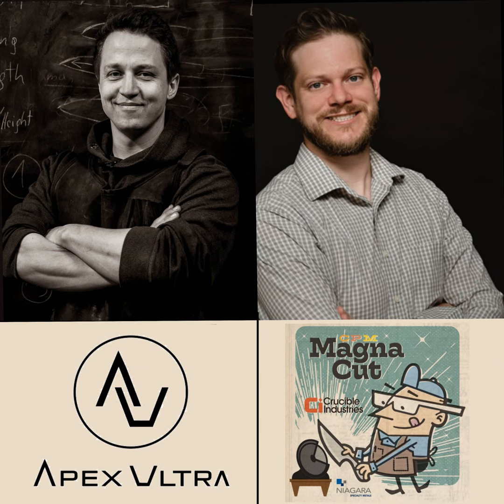So basically, quench as fast as possible and as slow as necessary, not to get cracks and warping. I have no intention of using copper plates. No, I wouldn't even say it's a bad idea if you have a production process focused around petties or folders and stuff like that. We would have to test it. And I'm not even sure if you really have slower cooling rates in the upper temperature range than using oil, if you use enough pressure and if your metal-to-metal contact surface area and the heat transfer is good.